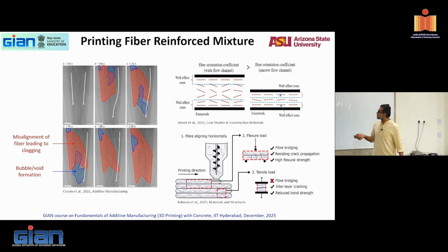Printing fiber reinforced mixes, just to give you a few examples. Remember the wall effect that you saw with aggregates, where things will get stuck onto the wall and create a different packing closer to the wall? Same thing here also. You will have fibers there, and in between you will have fibers all randomly aligned, depending on the size and the effect. But as you come through the nozzle, effectively, if the fiber dimension is anywhere close to the size of the nozzle, you will have aligned fibers. If the fiber is extremely small as compared to the nozzle size, you will still get random orientation.